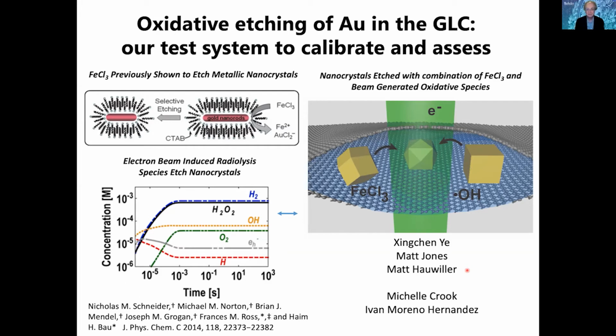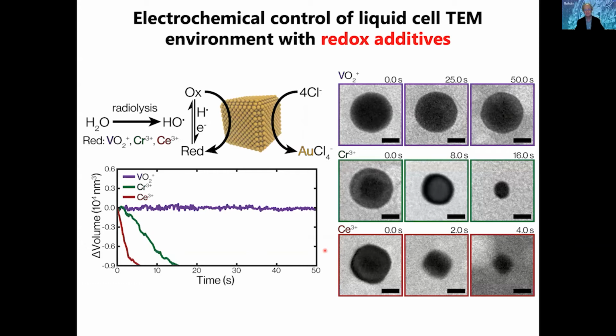And that beam can, of course, create all kinds of chemistry inside the liquid environment, and that chemistry can act to etch the nanoparticle. And so we try to understand this liquid environment. It's a very complex one. Ultimately, a measure of success for us would be if we could do something so that inside the liquid cell, it behaved as if we had an electrochemical electrode where we could set the chemical potential inside the liquid cell. So I'm going to show now some experiments which we believe indicate that we have found a way to do that in a very simple way.